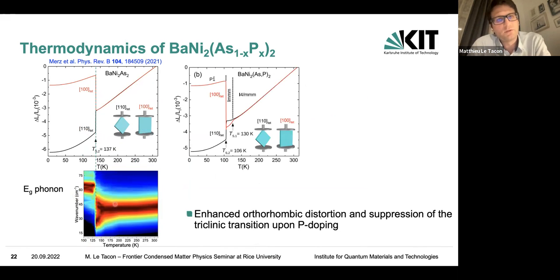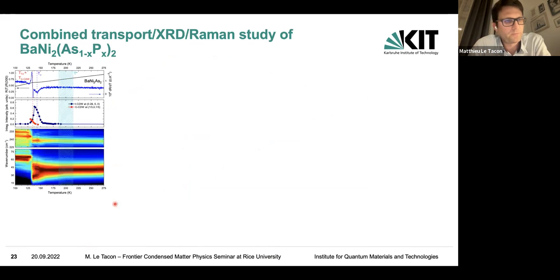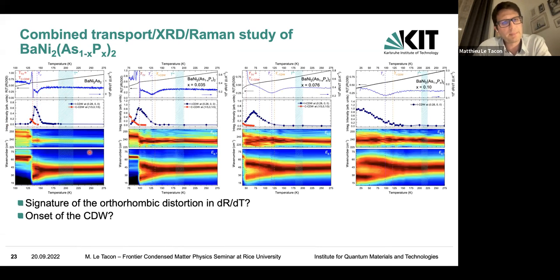So we decided to check what was going on in the phosphorus-doped samples, and we looked at the whole series and compared in a somewhat systematic fashion. We measured the resistivity and the derivative of the resistivity. We looked at the intensity of the incommensurate charge density wave and of the commensurate charge density wave as a function of doping. What we find is that this splitting of the EG mode remains up to 10% doping. So we still have a very nice splitting here. The splitting is up to like 60% of the mode frequency. The second EG mode, which is a bit weaker at higher energy, we don't really resolve the splitting, but it clearly broadens as well. So it feels something as well.